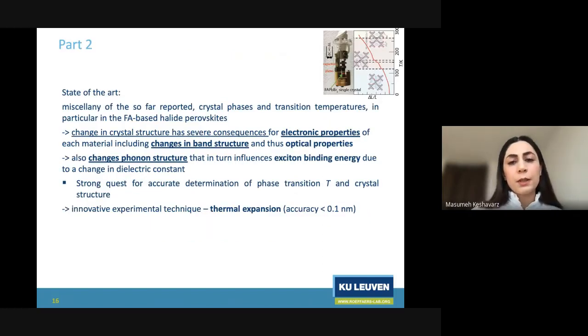In part 2, the state of the art was that the structural transitions and phases were reported differently for the same material, for the same temperature ranges. Why is it important to know the structural properties of the material? Because changes in the structure can have effects on the electronic properties of the material. It can change the band structure, and from that, the optical properties. Also, it can change the phonon structure, which affects the exciton binding energy.